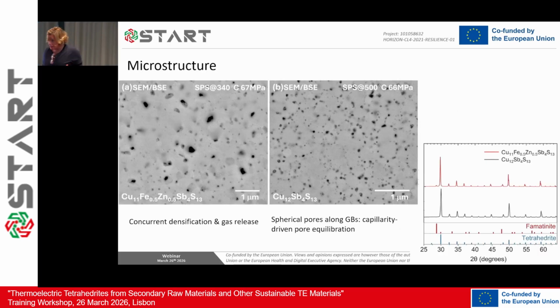So when we look at the microstructure, what we saw was that in all cases, there was not one single sample that I've observed until now, and we produced hundreds of samples, that didn't have porosity. There's always porosity. We only use SPS, so we don't have any hot press results.